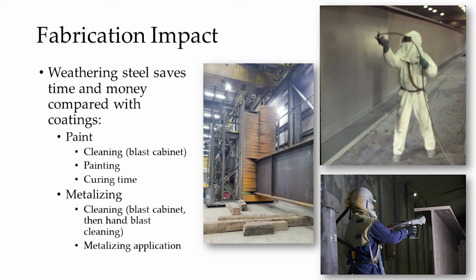It's worth noting the difference in the application. If you look at the top right, you'll see a painter. Bottom right, you'll see a metallizer. Significant difference in that gun, right? Look at the size. The metallizing gun has the zinc wire feeding to it and also a current, because we use an arc to melt the zinc plus air. So you're spraying on with air, you're melting the wire with an arc, and you're delivering the zinc. So there's a lot of stuff to come together in that gun. It's a rather heavy gun, and you see the size of it. So it's well suited to large spaces, but not small ones.